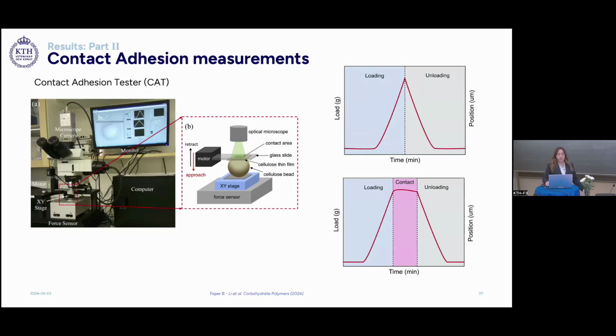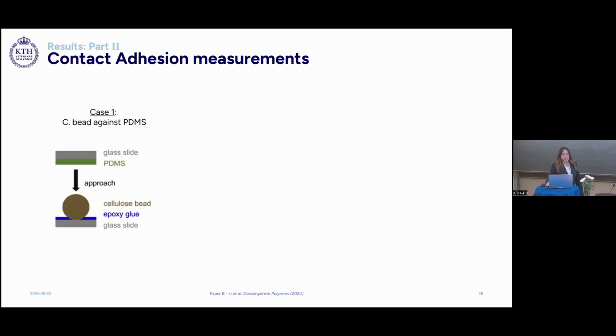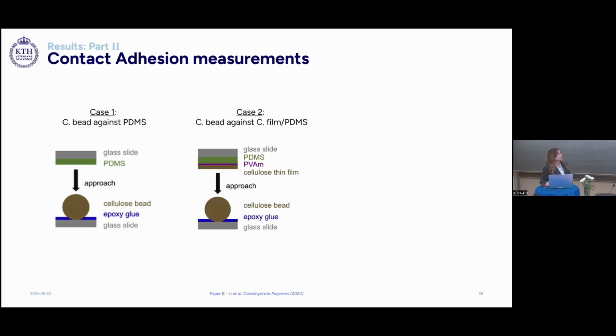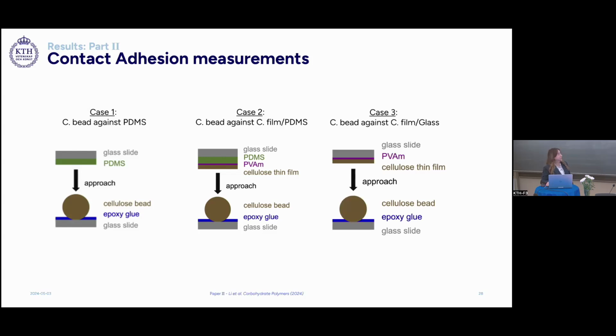Typical curves can look like this, showing loading and unloading curves. We can either load the two materials until reaching a trigger value and then directly separate them, or we can keep them in contact for a certain time before unloading the two materials. In this project, we tested 3 different cases. Case 1 is a cellulose bead against a PDMS surface. Case 2 is a cellulose bead measured against a cellulose film spin-coated on PDMS. And case 3 is a cellulose bead measured against a cellulose film spin-coated on a glass slide.